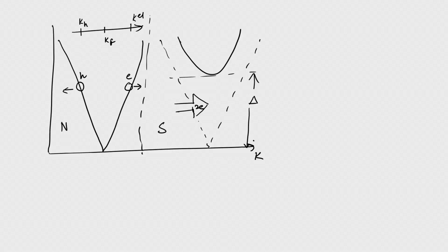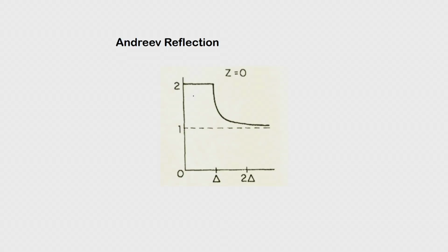So, this is called Andreev reflection, and to see that we have current at almost 0. So, basically you see that below delta there is a current which is pretty large, and then of course beyond delta the current goes down for a reason that also can be explained simply. So, this is the feature of this Andreev reflection, and it is present in all normal superconductor junctions, or even if one introduces a barrier between the normal and superconducting junction. Just to say that the normal is usually a metal such as aluminum, etc., and sometimes an insulating barrier is introduced between the normal and the superconducting junction. One can do the same experiment.